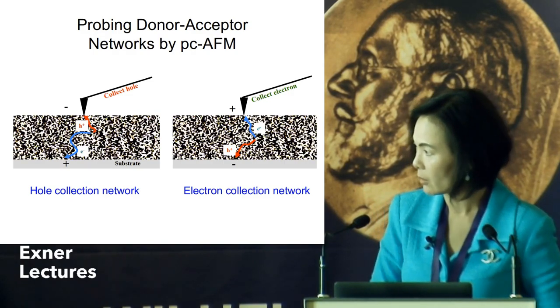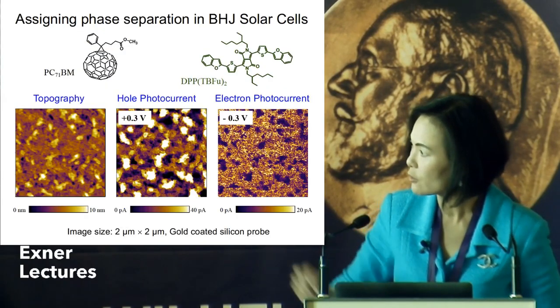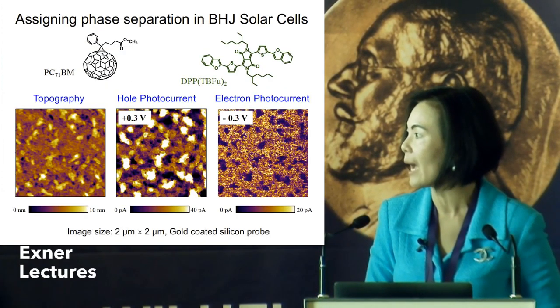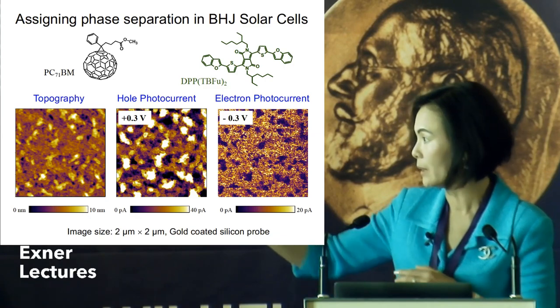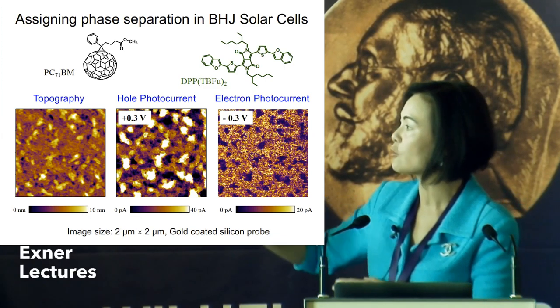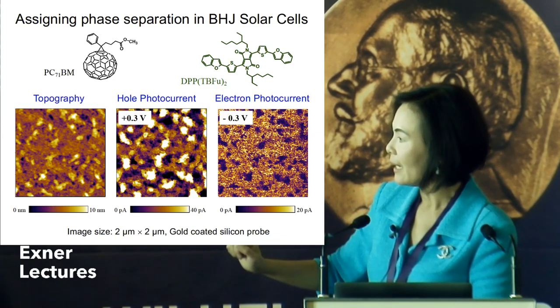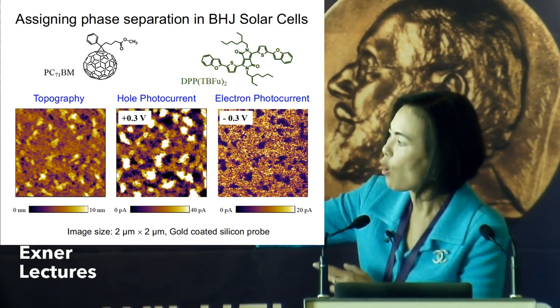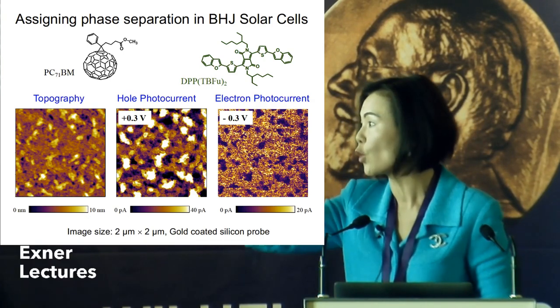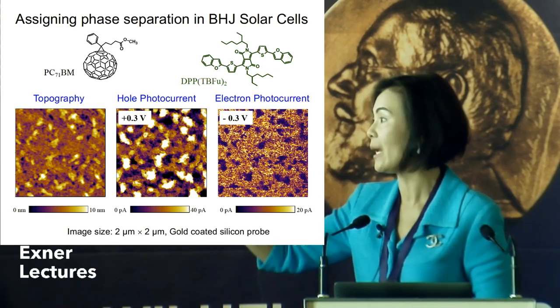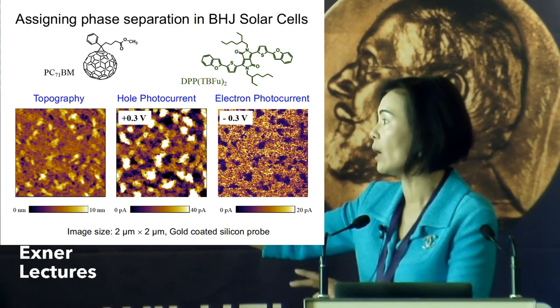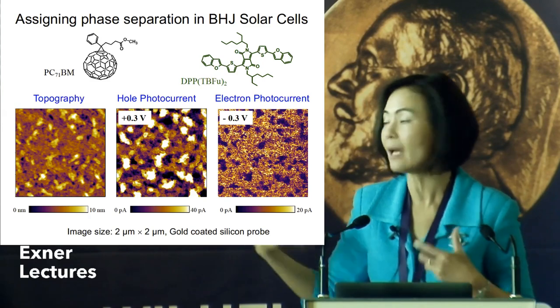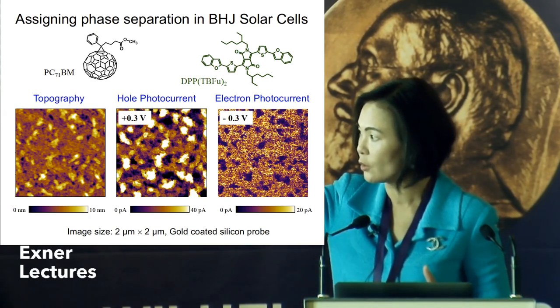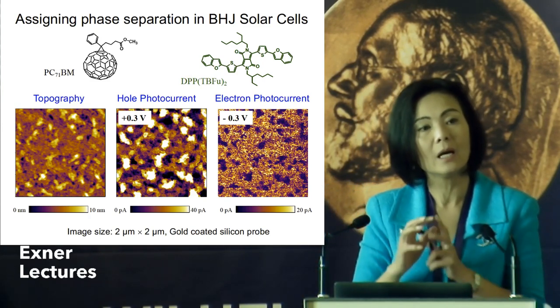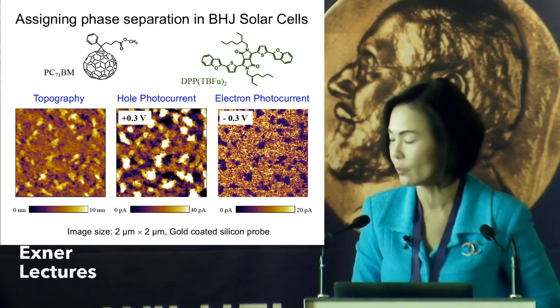For example, here on the far left image, we see topography, and then you have the hole photocurrent in the middle, and the electron photocurrent on the right. And you can see basically the tall feature has high hole photocurrent, where you have almost zero electron current in the subdomain. So that allows us to assign the sub-feature you see in topography as actually donor material.